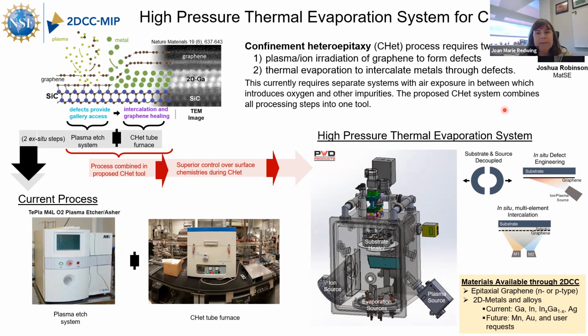So the CHet process involves the intercalation of metals into the van der Waals gap in epitaxial graphene that's formed on silicon carbide. And defects in the epitaxial graphene play a key role in the intercalation process. But the two processes are currently carried out in separate systems where defects are formed, and then a separate system is used for intercalation. And there's air exposure of the samples in between, which can cause some problems. So what we're planning is a new system that's going to have an integrated plasma source and a thermal evaporator, and that will enable both of those processes to be carried out sequentially in the same vacuum chamber.